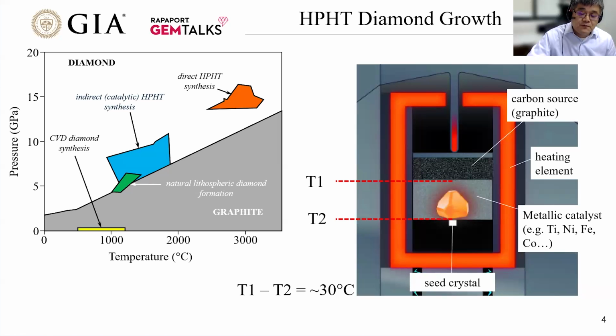But for HPHT lab grown, the blue area indicates the pressure and temperature condition. Slightly high pressure and a slightly high temperature. Basically, it is mimicking the natural conditions to grow diamond. As you see here, we marked the yellow area as the CVD diamond growth condition, about 1000 degrees C minus plus 200 degrees, but the pressure is close to 0. So it is almost in vacuum to grow CVD diamond, but HPHT is mimicking natural conditions.